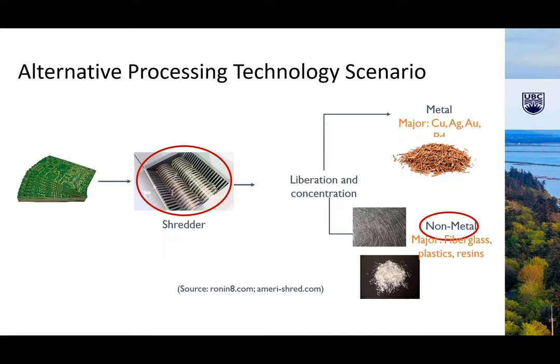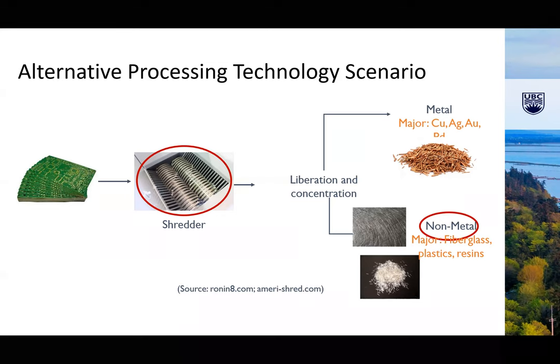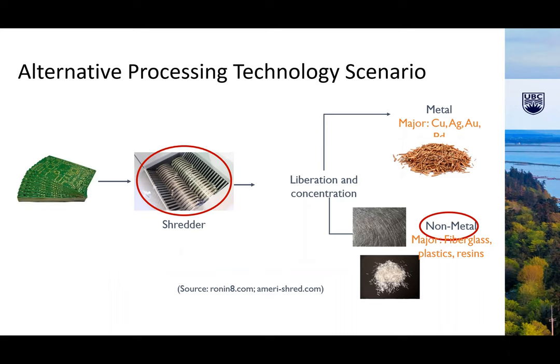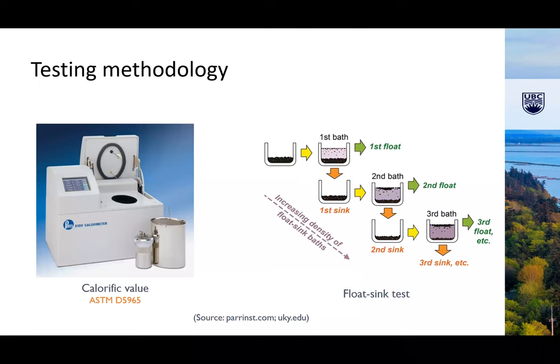So the material was not pure, not brand new circuit boards, but there was the waste, electronic waste circuit boards were shredded, then they were crushed by hammer mill. Liberation was done by their patented technology, sonic liberation, in combination with the water-based shaking tables. So as you can see, the idea was to actually make sure that we can scavenge and we can separate by physical and using water cleaner processes. So metal was extracted, and what was left was non-metal fraction that we got to work with.